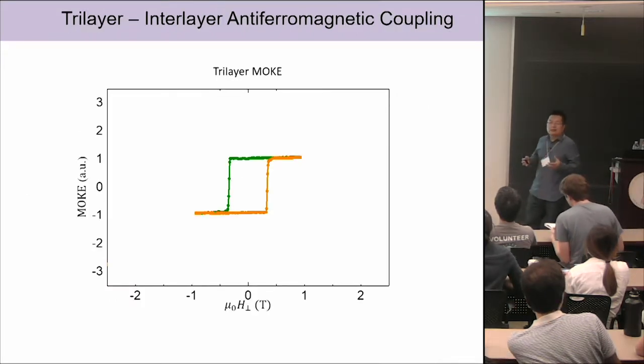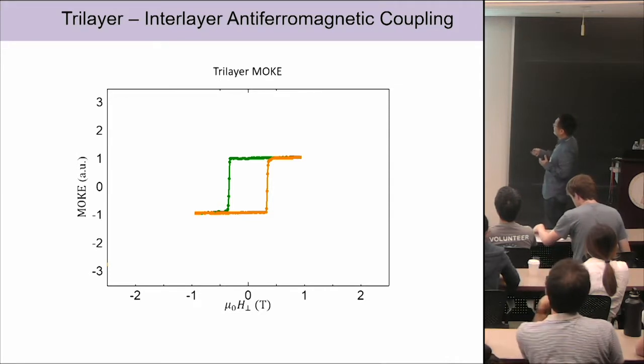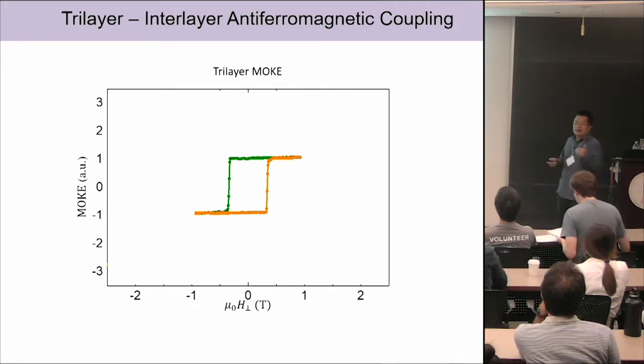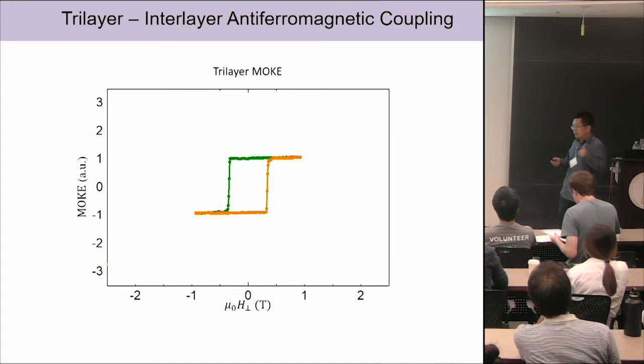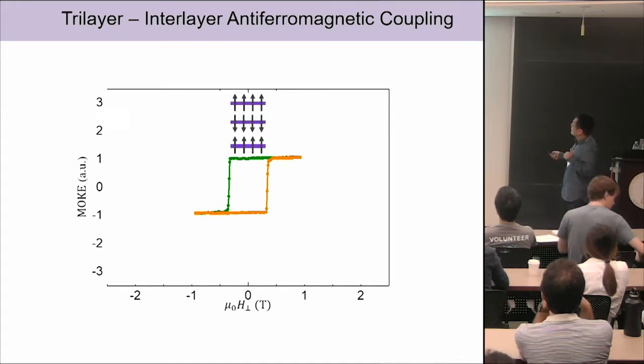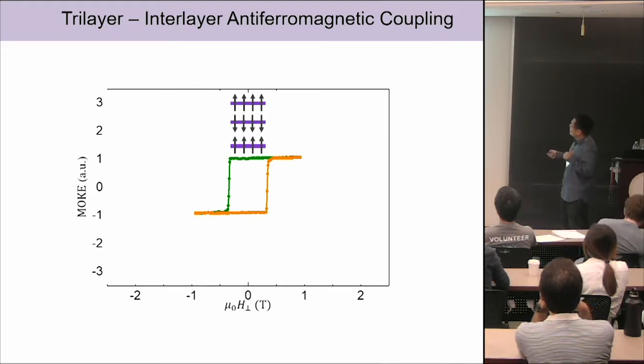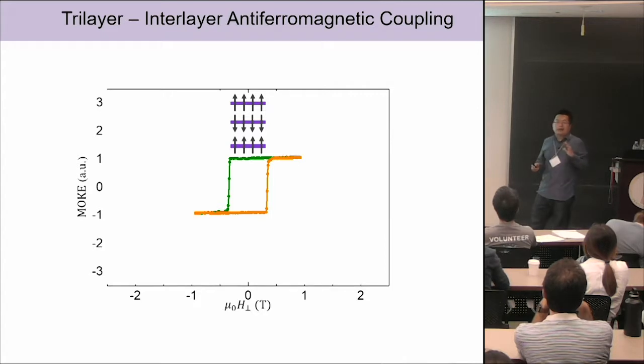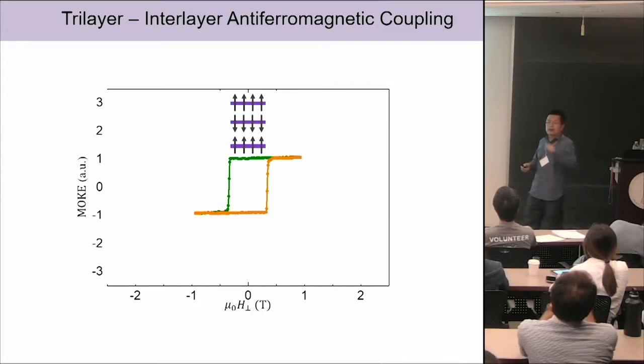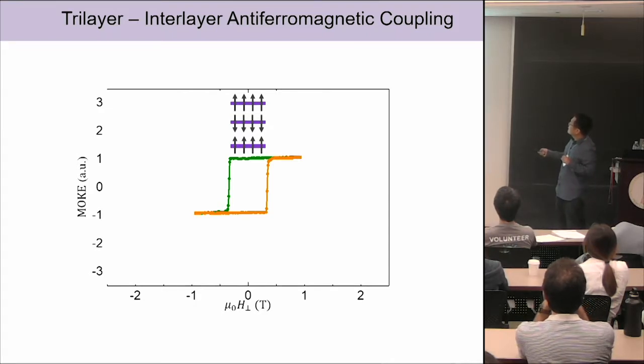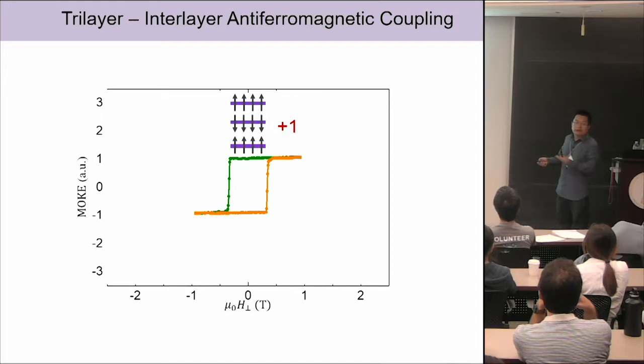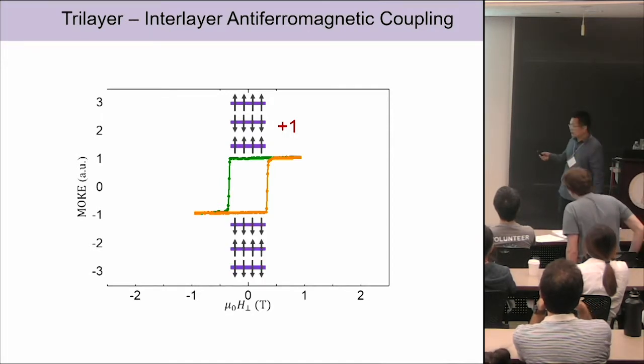Then we can extend this concept to the trilayer, so we can understand why the trilayer has a hysteresis curve. Based on the bilayer, we know the interlayer coupling is anti-ferromagnetic. So in the trilayer we should have a structure like this: for example, the top layer has spin pointing up, the middle pointing down, and the bottom pointing up. So we have an up, down, up configuration. If we consider the magnetization of an individual monolayer as a unit, which is 1, then the total magnetization for this state is 2 minus 1, which is just 1. Then there should be another state which is the time reversal of this, with net magnetization of minus 1.